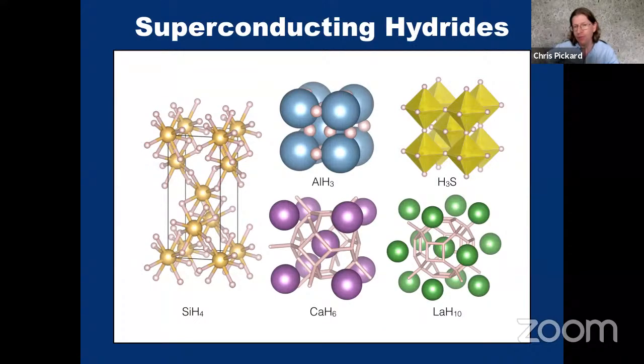And this actually was quite an important moment, because it showed Mikhail Eremets that it's worth listening to the theoreticians. The way he explains it, this or the aluminium hydride moment were moments when they thought, hang on a minute, these suggestions that the theoreticians are starting to come up with might be synthesizable, because he just synthesized it. So I moved from silane to aluminium hydride, and actually, unknown to me, Mikhail Eremets and others had synthesized it at the same time. I proposed that as a metallic hydride, it might be a superconductor.